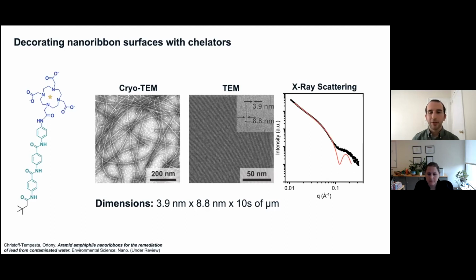We were able to show that in the dried threads, we maintain approximately 200 meters squared of surface area per gram, which is an enormous amount of surface area. And so thinking about how having all of that surface area accessible on a solid state material, as I mentioned, I'm really focused in the area of environmental remediations. I could think of things that might be present in air that we'd want to remediate as well, that would take advantage of that.